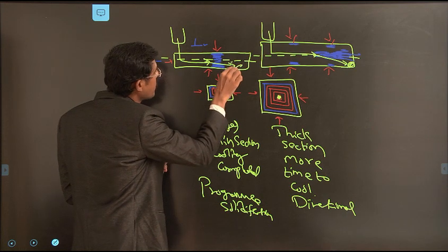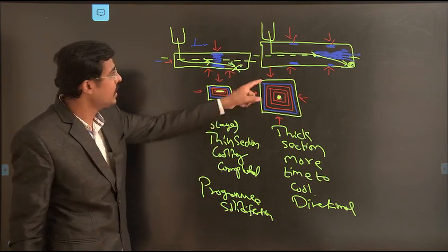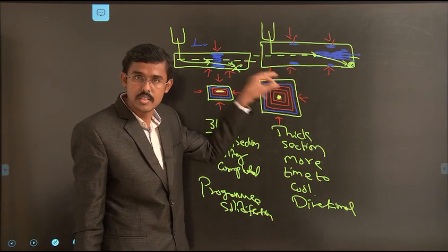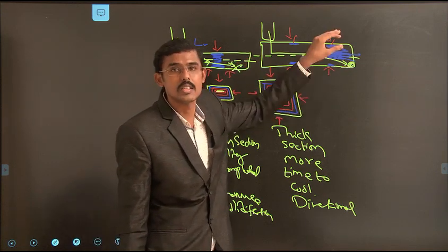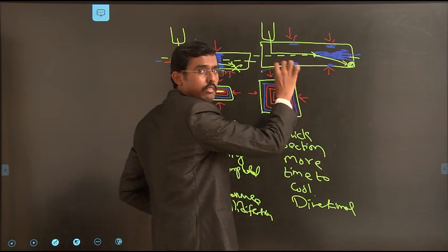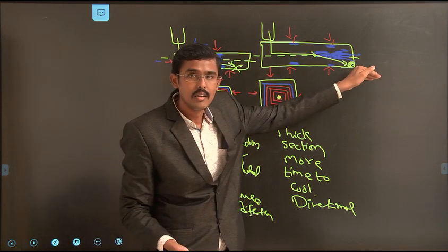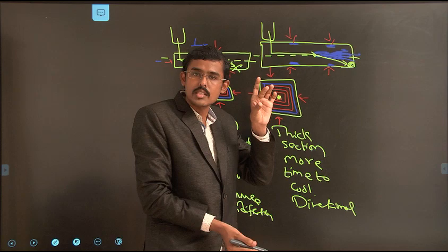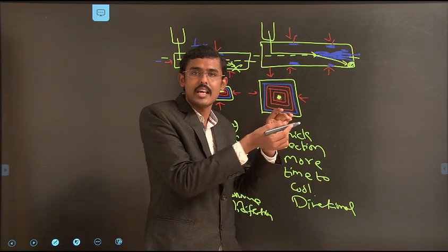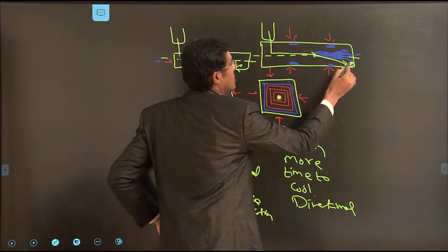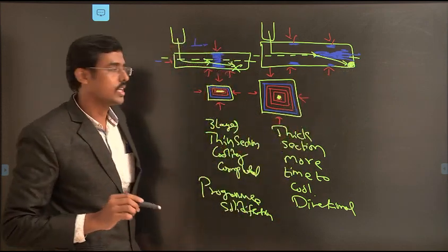But even though at the corners progressive solidification is there, at the center directional solidification is there, starting from the right side to the left zone. This feeding system works well because at the borders there is progressive, at the center there is directional, the feeder goes inside and it helps to reach the corner. So that is a point we should understand.